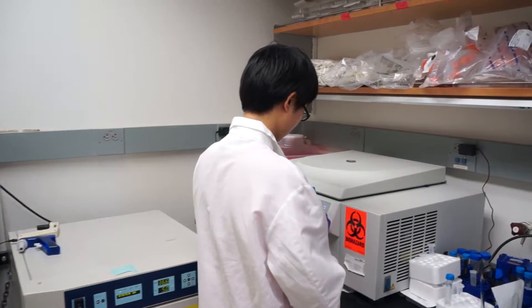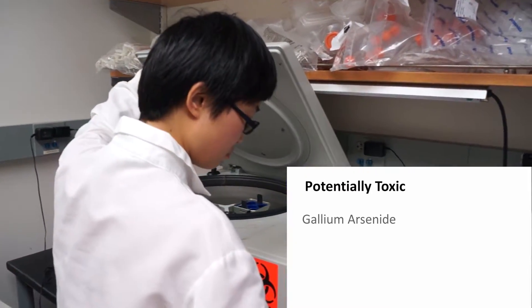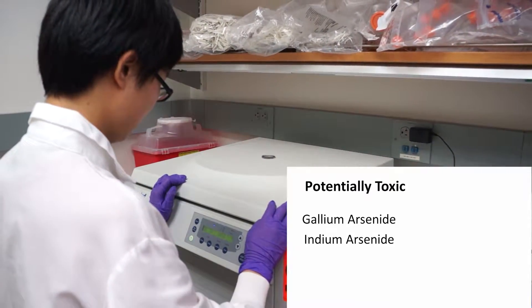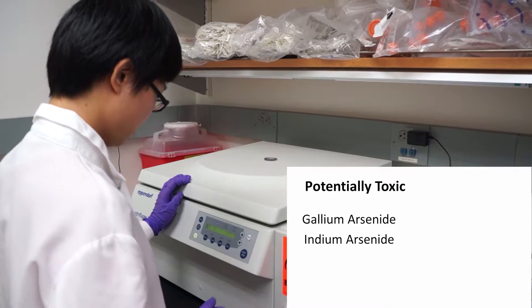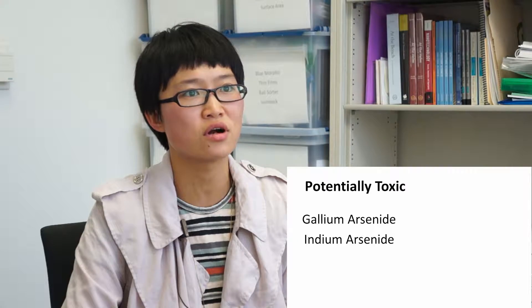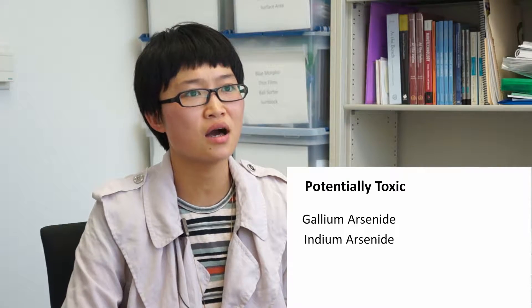We found that nanosized 3-5 arsenides, including gallium arsenide and indium arsenide, could induce more significant cell toxicity at 24 to 72 hour observation periods. In contrast,